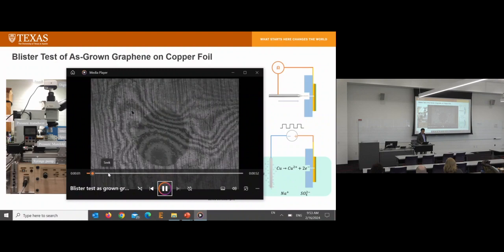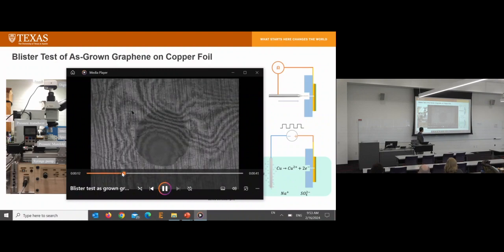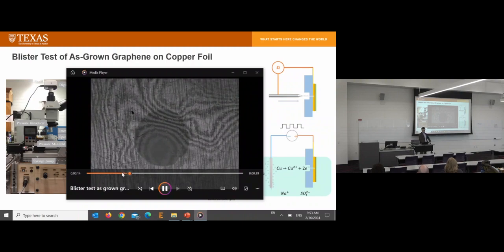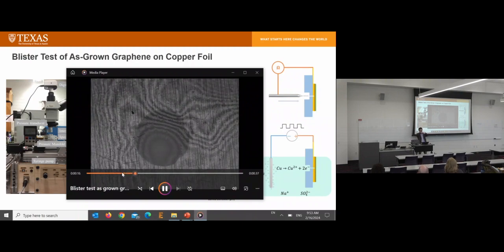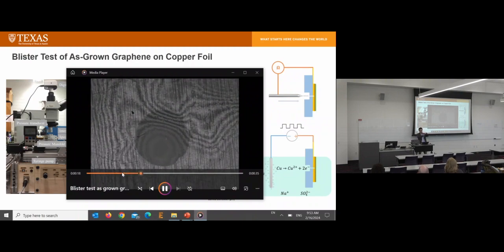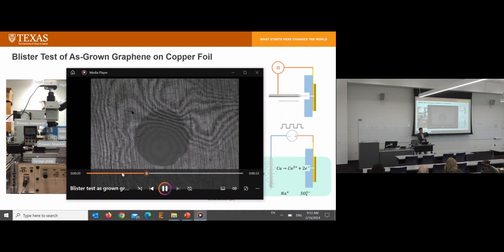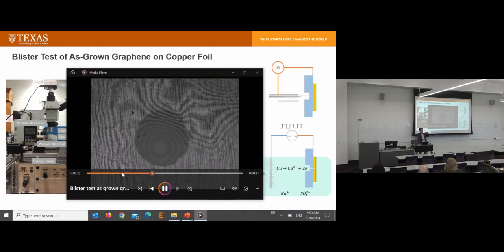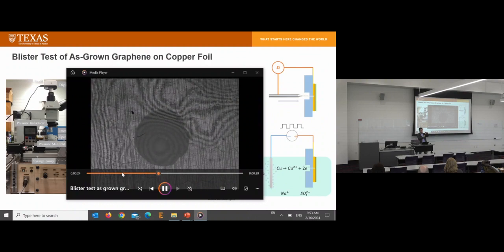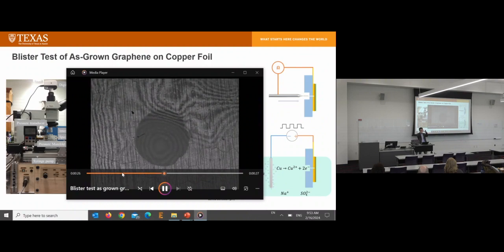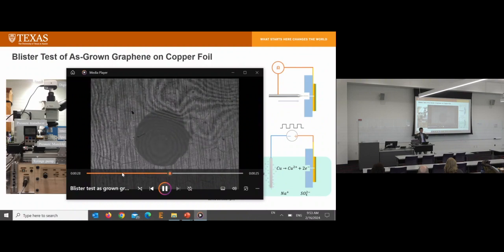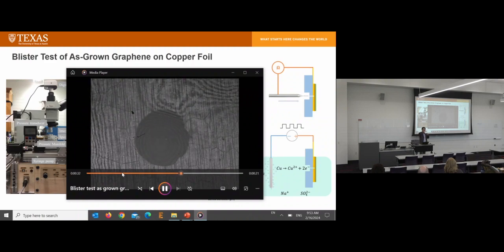So yeah, this is the actual test we did. Just on top, you have CVD graphene, and you have a hole through the copper foil, and then we supply water, and we use water to increase the pressure. You see the interference fringes form, and you can count how many fringes there are. You can calculate the height of that.